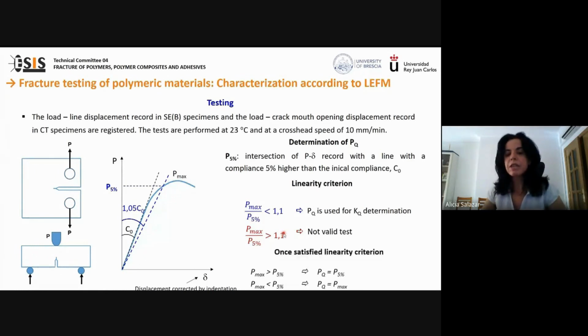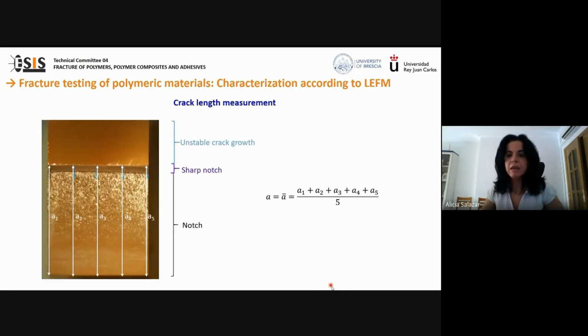Once the linearity criterion is satisfied, we have to define PQ. And we have two options. The first one, if the maximum load, Pmax, is higher than P5%, then P5% is equal to PQ. On the other hand, if the maximum load is lower than P5%, then PQ is equal to the maximum load. For the determination of the fracture parameters, we also need the value of the initial crack length, and this is obtained from the fracture surface.